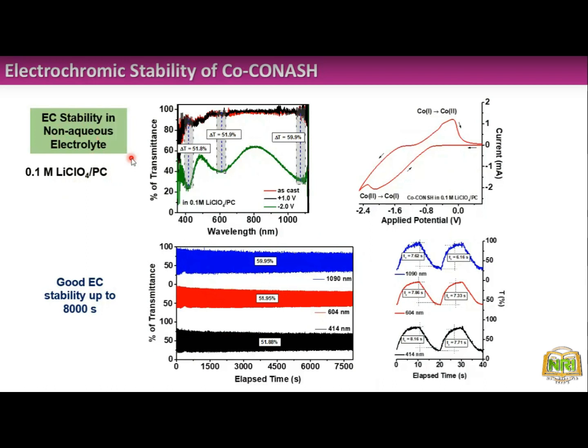So when we check again the electrochromic spectra over the whole spectral region, in the non-aqueous electrolyte also we are getting 3 separate peaks, and again all of them fall from the visible to the NIR region, and in almost all the region the delta T, like the color contrast, is very high. And we checked the electrochromic stability, and we have seen that up to 8000 seconds the compound is very stable. It is showing good data.